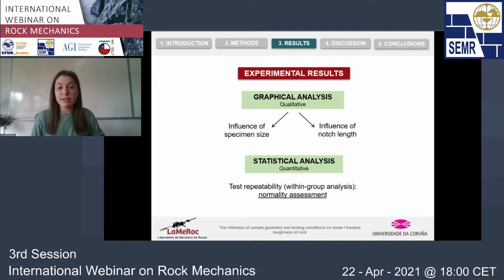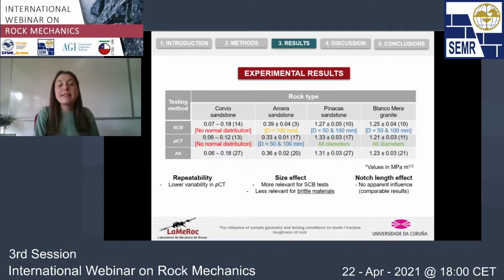influence of these effects. So we thought that it was a good idea to perform a statistical analysis to quantify these effects. So to assess the repeatability of the experiments, we have performed a normality assessment. So we have checked if the values that we got conform to normal distributions. And I'm not going to give many details about this statistical analysis, but these are the values that we got,